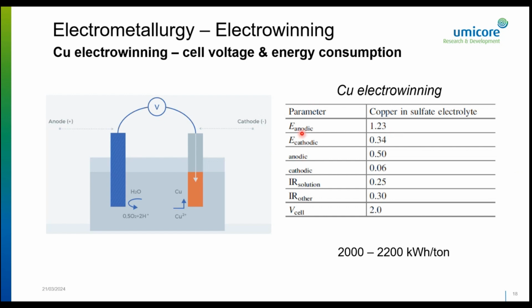So for instance, for copper electrowinning, you have 1.23 volts anodic potential and 0.34 volts for copper reduction. The difference between those two is about 0.9 volts. So in the most optimal conditions, you could operate the process at 0.9 volts, but in reality you operate the process at about 2 volts, and that's because you have a lot of additional potential